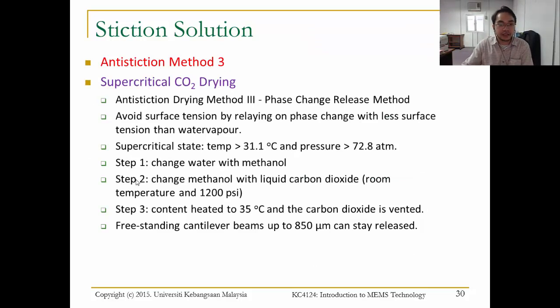Anti-stiction method number three is by supercritical carbon dioxide drying. This is also what we call the phase change release method. We can avoid surface tension by relying on a phase change with less surface tension than water vapor. Here we use carbon dioxide to dry our device. At this supercritical state, the temperature is above 31 degrees Celsius and the pressure is above 72.8 atmospheres. These are the parameters needed for this process.